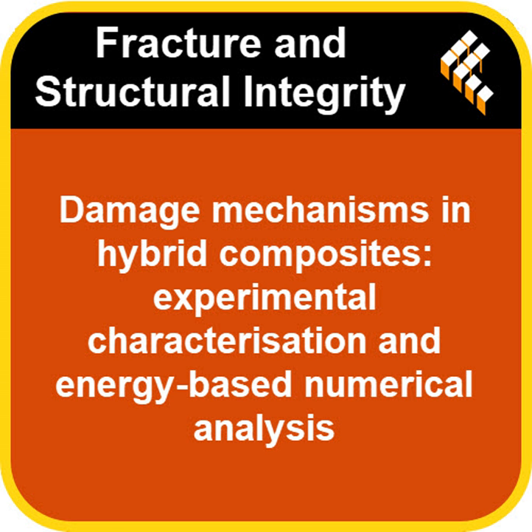If the glass was on the squished compression side, it was the outermost carbon layer on the stretched tension side, layer #1, that experienced the most damage energy dissipation. Okay. If the glass was on the stretched side, it was the outermost carbon layer on the squished side, layer #8, that saw the most damage. So the outer carbon layer opposite the glass took the brunt. That's what the energy analysis suggested.